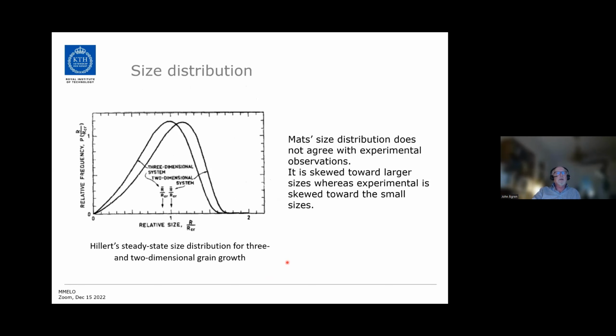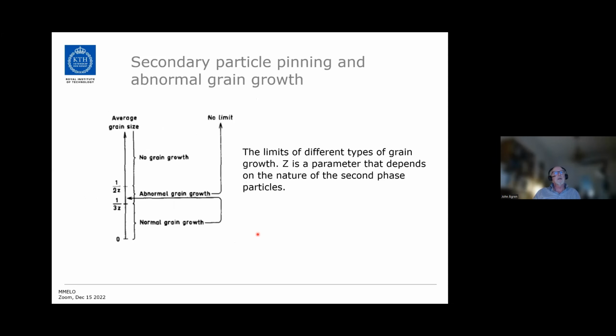But he could also calculate the grain size distribution, and that does not agree well with experimental data because it is skewed towards the larger sizes, whereas experimental data is skewed in the other direction, towards the smaller sizes. Then he also discussed the secondary particle pinning and the tendency to abnormal grain growth.